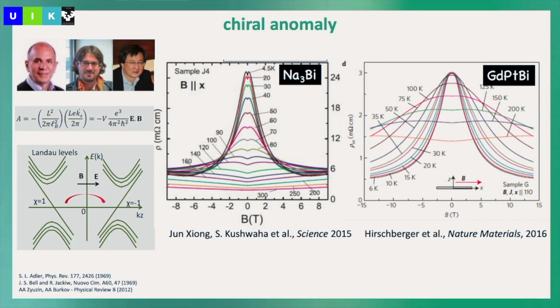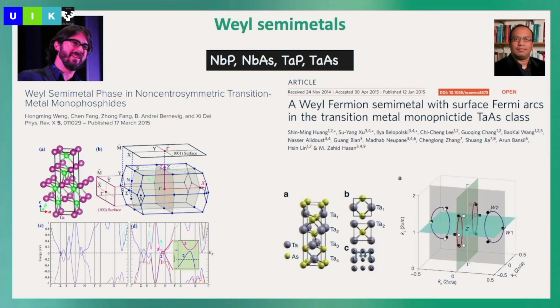Dirac semimetals, sodium 3 bismuth and gadolinium platinum bismuth. This is a Heusler compound. So there they really saw this negative magnetoresistance, but it became, again, it's a lot also in this field of topology. In the moment when you have a simple material, which is nice to tune, because you can go from lighter elements to heavy elements, so you increase relativistic effects, spin-orbit coupling, and they are quite easy from their electronic structure. So these semimetals, when they were predicted, with this very simple structure, 2 elements, not too complicated band structure, and so on, this field of semimetals was really, I think, boosted.